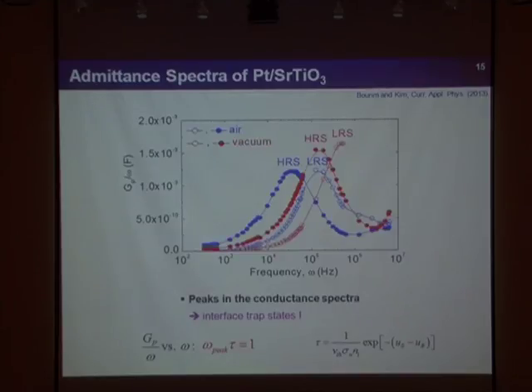So this shows the result. We can find features from this conductance versus frequency curve. This means that the trap states model really works, so our device really has interface trap states.